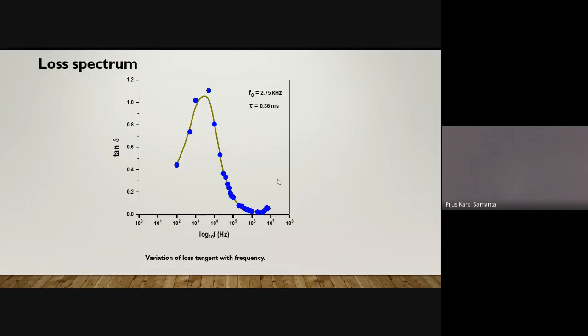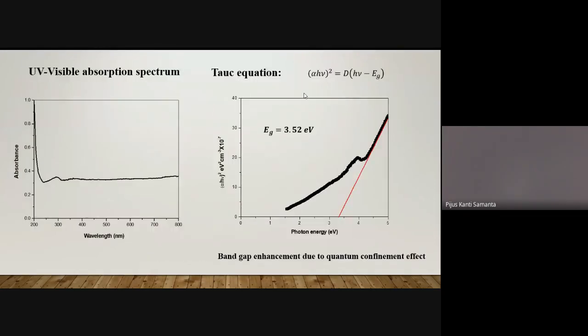And the relaxation time we found is quite low. This is 0.36 millisecond in case of our samples, and this was calculated from this graph. And this decrease in the higher frequency region may be attributed to the accumulation of space charge in the high frequency region. The optical properties of the material were studied by observing UV visible absorption spectrum and photoemission spectrum.